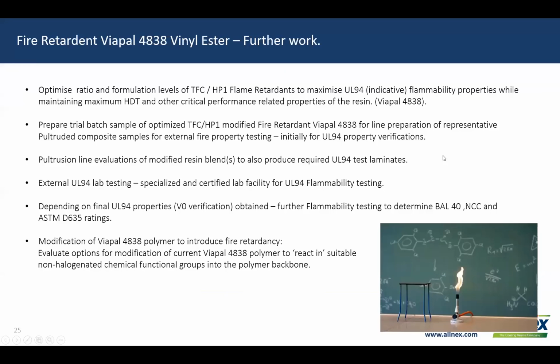Okay, so further work that we have, we need to optimize the ratio and formulation levels of these two flame retardants for this particular part, just to maximize the UL94 fire retardancy properties and maintain the maximum HDT. I believe that's been done. So we're really at the stage now that we want to prepare some small trial batch and even some lab batch samples, which I believe that the guys can run at USQ, possibly at Wagner's as well, in a smaller scale trial. The main reason there is to have a look at the line processing and curing properties. The guys can obviously have a look at this through their DEA analysis tools as well, to compare how this would compare against the current non-fire retardant version of the resin.